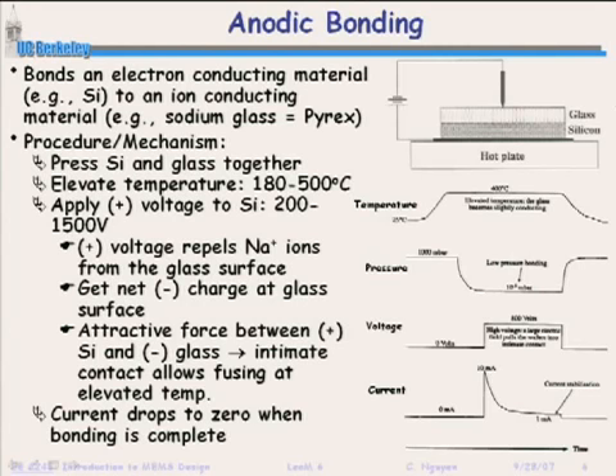You then apply a positive voltage to the silicon. And it can be a very high voltage, from 200 volts to 1,500 volts. The positive voltage repels the sodium ions in the glass. So at this high temperature, those ions become more mobile. Right? So that's why you've got to get the temperature up a bit so the ions can be mobile. And that electric field then pushes those ions away. You get a net negative charge at the glass surface then. And that negative charge together with the positive charge on the silicon really compresses all of this together so that you can get strong attractive forces and an extremely strong bond between the glass and the silicon. Okay, so this is anodic bonding, another very useful method for bonding.